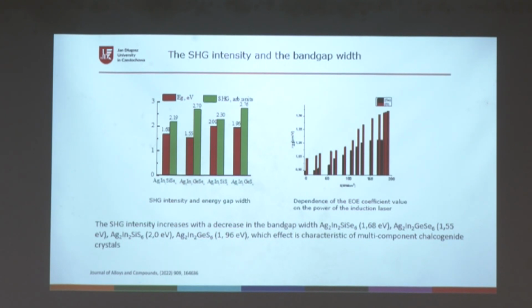And here are some results of investigation when we compare the efficiency of second harmonic generation with the band gap of materials. Because we found some correlation investigating properties of several single crystals, which gives us the opportunity to find a tendency. Yes, one of the conclusions is that second harmonic generation increases with a decrease of the band gap.